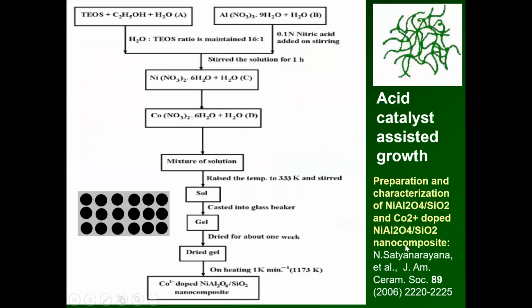So this is the one under acid catalyst. This paper has got so many citations, and this took about 6 months by one PhD scholar and postdoc, and it has given a lot of good citations. So what happened here? We developed two nanocomposites. One is nickel aluminate nanoparticles dispersed in SiO2. The second one is cobalt nickel aluminate nanoparticles dispersed in SiO2.